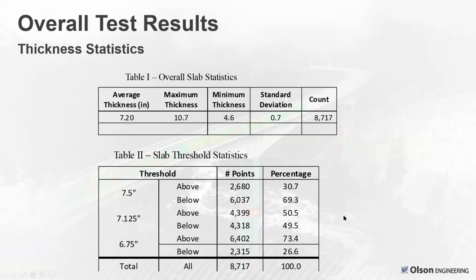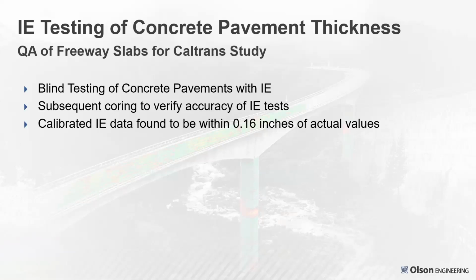We also, by the way, did some calibration tests with single point impact echo in areas where we knew the slab thickness along the edge or next to some cores. So we had some known slab thickness locations for calibration. And to verify that the impact echo method can be used for this particular application, we had done a number of years ago an impact echo testing study with Caltrans on freeway slabs, to look at how accurate the impact echo test method can be for measuring slab thickness.